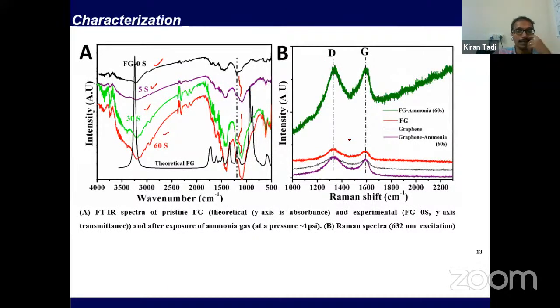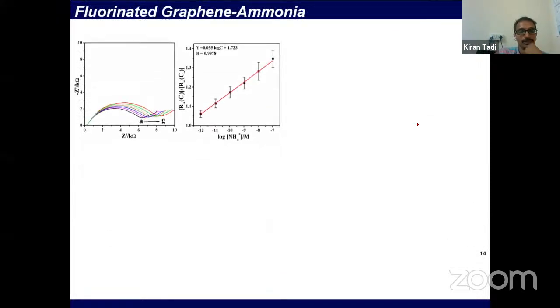But here the ID by IG ratio clearly shows there is no difference between before and after exposure. Then we went to electrochemical sensing using impedance spectroscopy.